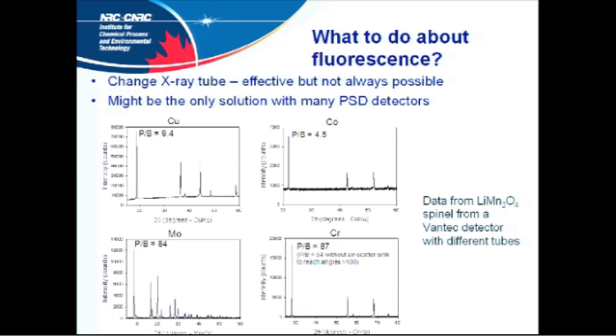What can you do about it? If you're lucky and you have the time to do it, you can change the X-ray tube. This is the most effective way of dealing with it. You can see here, this is a manganese-based spinel. The copper, which is your common one, is not particularly wonderful, and this was a PSD, by the way, so there's no monochromator. The cobalt is really bad. And this is unfortunately our routine setup currently.